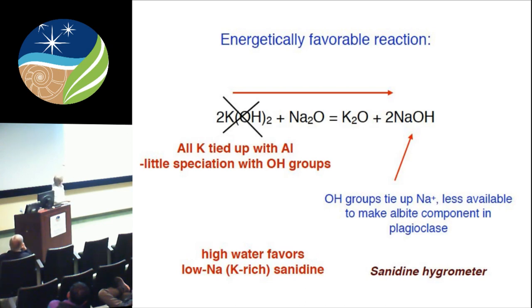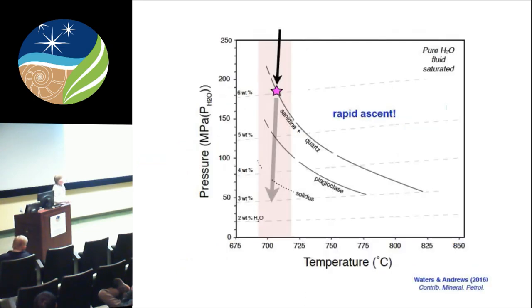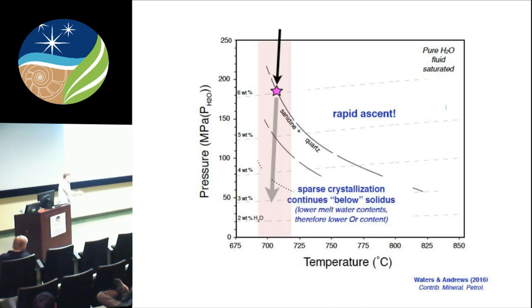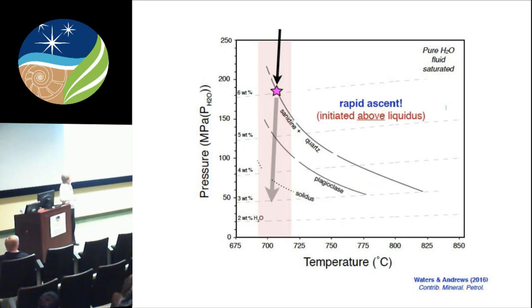And so as this rhyolite is ascending, it comes in and crystallizes just sanidine and quartz, then plag. And the reason it can get all the way down, reflecting lower water contents and a more orthoclase poor sanidine, is because it's able to go below the equilibrium solidus because it's going so fast. In fact, we know this rhyolite erupted, right? It erupted with only sometimes 1% total crystals. So there's definitely kinetic suppression. Now, the key is that you're only going to get this weird kinetic hindrance in big crystals if the magma begins its ascent above its liquidus, if it starts out without lots of little nuclei.